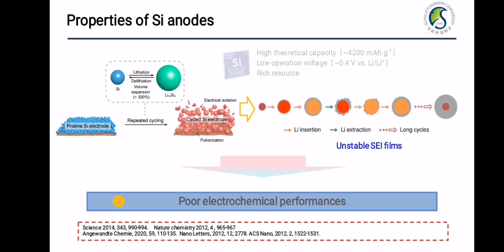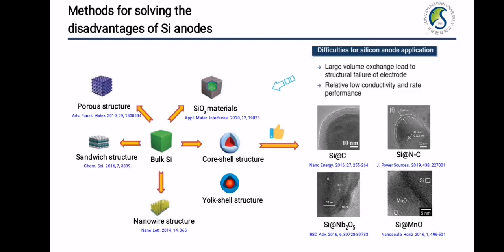However, during cycling, the large volume expansion of silicon will lead to the breakage and smashing of silicon particles, making the active substance unable to contact the collector closely, and it will generate an unstable solid electrolyte interface, leading to poor electrochemical performance. Researchers have done a lot of work to solve these problems, and the most usual method is using coating materials to build a core-shell structure. We can use carbon, metal oxides, MOFs, graphene, and so on.